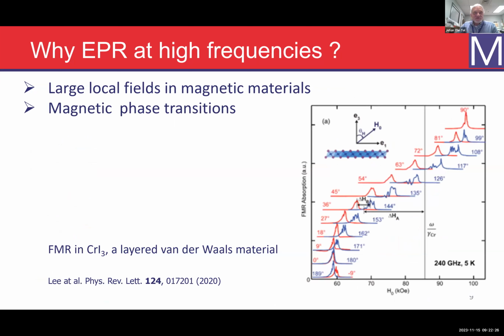And then another reason is, of course, that if you don't look at EPR in principle, but at ferromagnetic resonance or antiferromagnetic resonance, you get large local fields in these magnetic materials due to the exchange interaction from the surrounding centers. And you can also get magnetic phase transitions. So at different fields, your material might be in a different magnetic phase. This is just an example, also at 240 gigahertz, of ferromagnetic resonance in chromium iodide.